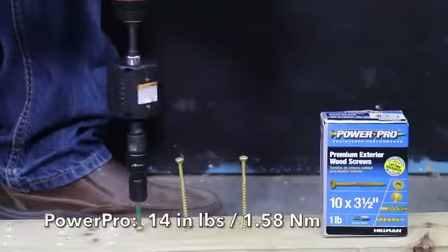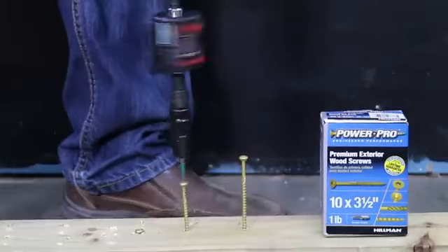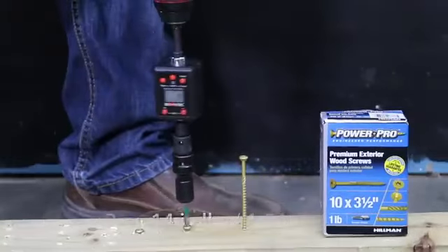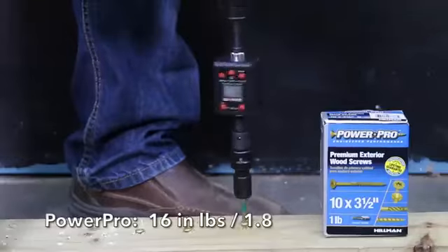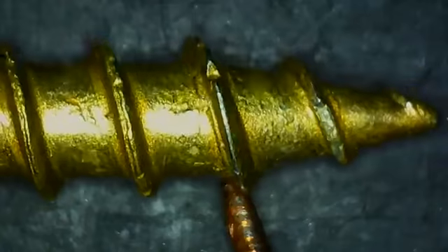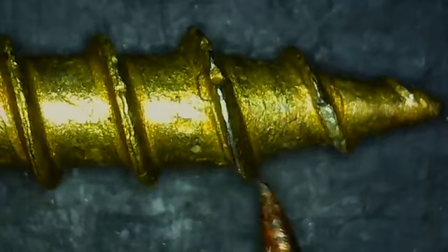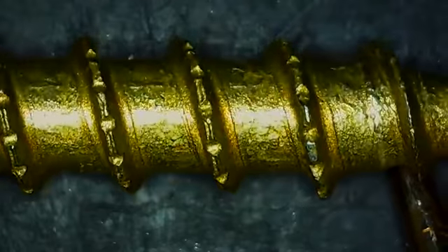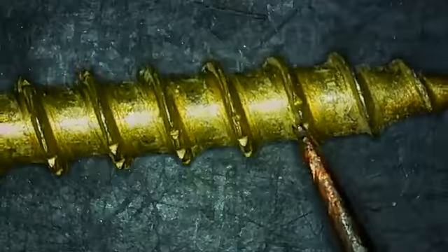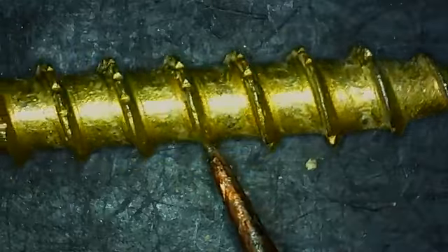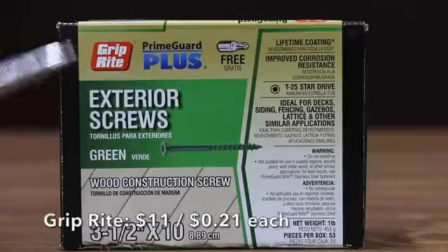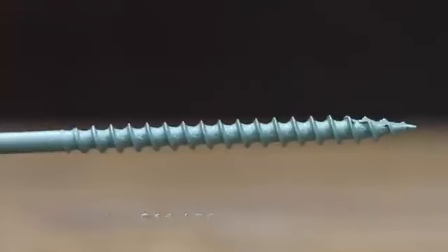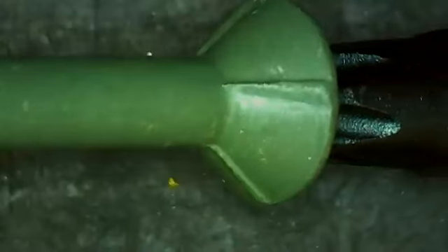And the PowerPro only needed 14 inch-pounds on the first drive. 14 inch-pounds once again on the second screw. 16 inch-pounds on the third screw, for an average of 14.7. The coating on the PowerPro seems to have held up the best yet, with very little metal exposure on the threads. The PowerPro also seems to have held up the best yet on the oak, with very little metal exposure on the threads. At a price of $11 for 53 screws, or 21 cents each, is this Grip Rite brand, which is sold at Lowe's and Home Depot.